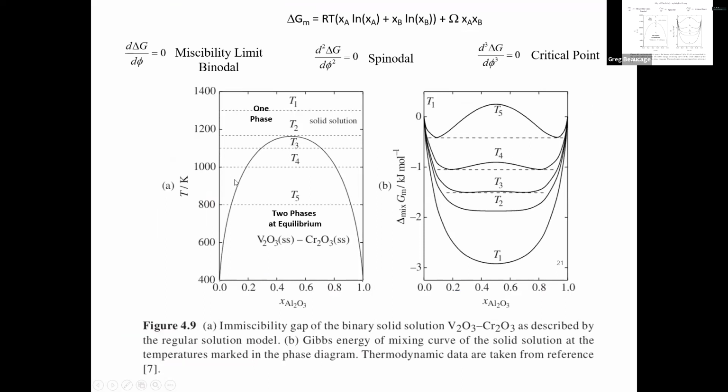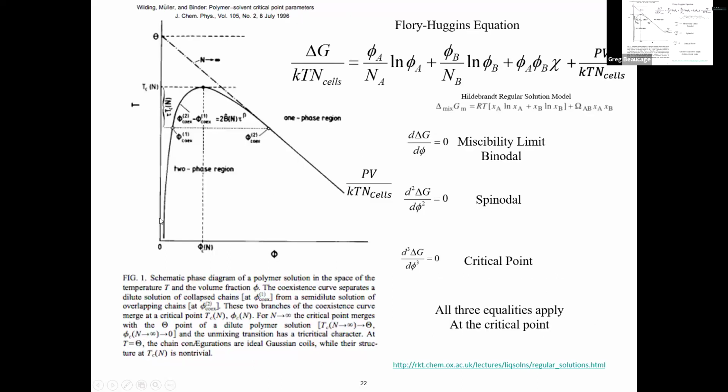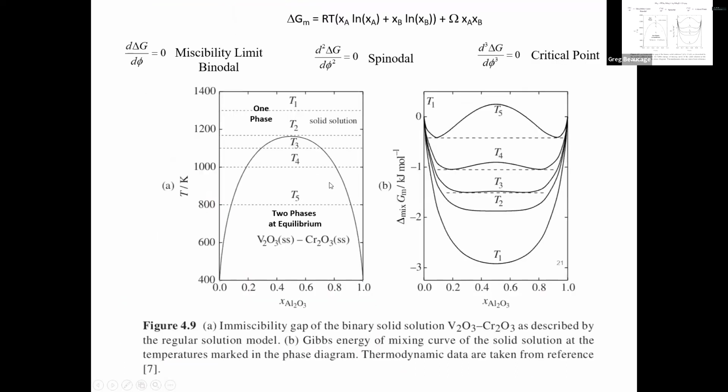Instead of being symmetric like that, it's skewed over towards the solvent end of things. So this is concentration of polymer, volume fraction of polymer. And then it's going to show the same kind of U shape, but it's shifted to the left significantly. Like the high end of this is like 1%, 10% or something. So it's significantly shifted over. This isn't a full scale to 1 here, whereas this thing goes to 1.